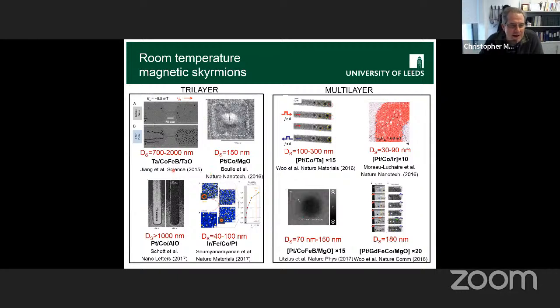So you have a magnetic layer, which is very thin, so that its properties are dominated by the interfaces. It's often cobalt or something that's got cobalt in it. And then you have above and below at least one heavy metal and maybe two. And they give rise to the DMI properties that are needed to create the skyrmions.